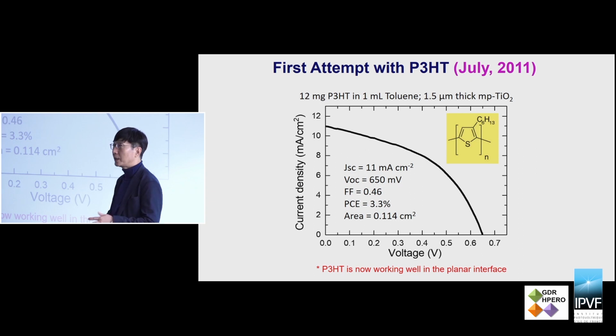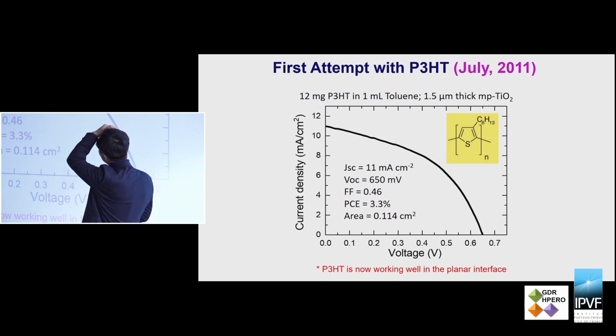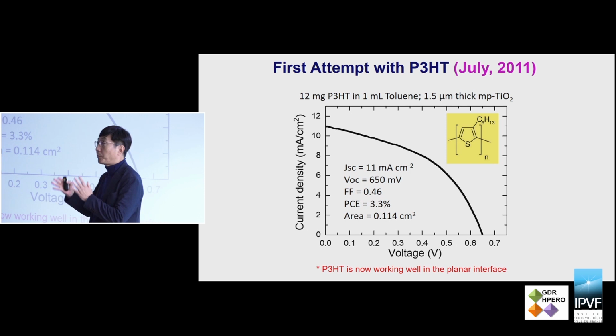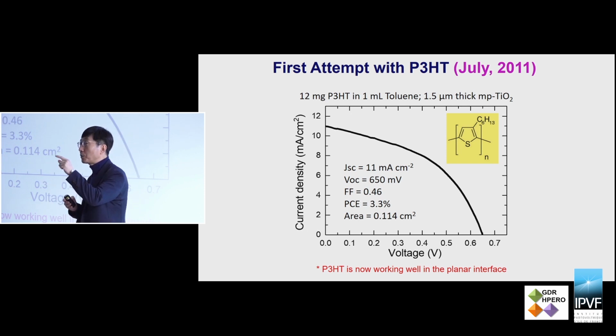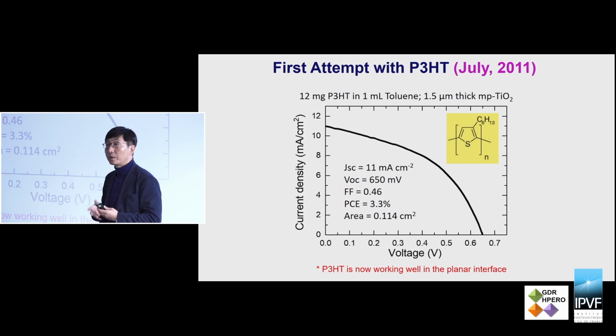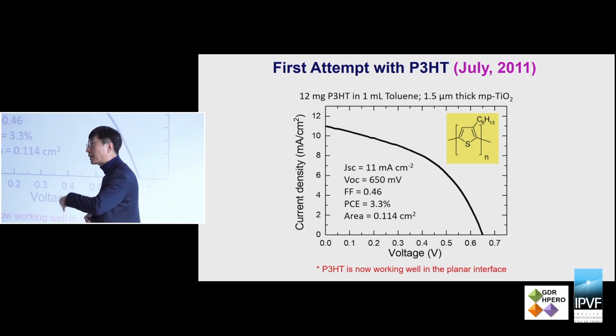So we would like to replace the liquid electrolyte with a solid hole conducting material. First we tried P3HT, which is well known for organic photovoltaics. But at first we did not get high efficiency, because we prepared mesoporous titanium oxide, and on its surface we adsorbed the dot morphology of the perovskite, which is then fully wrapped with the solid hole conducting material. In that case, the polymer should be infiltrated into the mesopores of titanium oxide. Polymer is very hard to infiltrate completely into the mesopores of the titanium oxide, so at that time we could not obtain high efficiency.